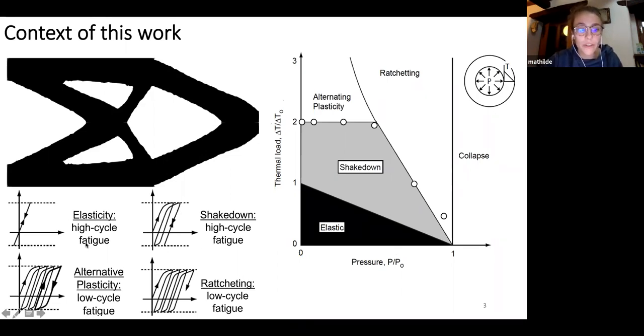So in this figure, we see that we have two different behaviors that allow this. The first is elasticity. In this one, we don't allow any plastification. And so in the Bree diagram, we see that it is this part. And then we have another one, which is shakedown, in which we allow some plastification on the first cycles. And this first plastification then brings the object back into an elastic behavior. And so we then can cycle many times without resulting in cracks. And we see that the shakedown part is here. So we see that actually the elastic, the non-plasticity behavior, is a special case of shakedown.